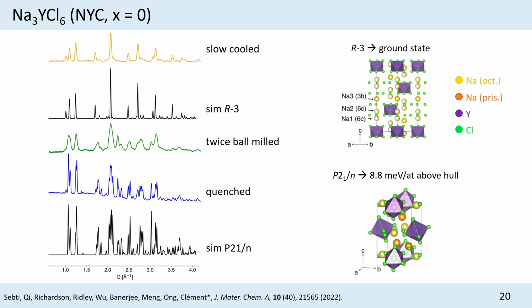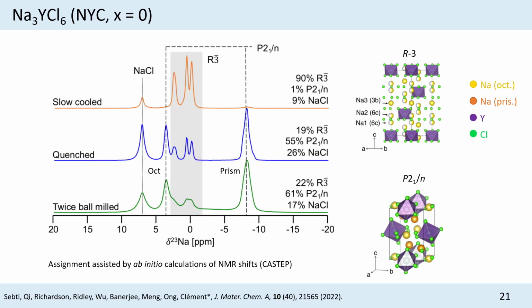If now you quench or you ball mill, you see a much more complicated pattern, and you clearly have also some P21/n polymorph here, which is above the hull. Again, what's nice with NMR is that you can quantify, and you can also assign these peaks quite well if you're doing first principles calculations of NMR shifts. Here we have 3 peaks that we can assign to the R-bar-3 structure. So these are 3 sodium environments in this structure shown here. And in this particular slow-cooled sample, we have mostly the R-bar-3 phase.